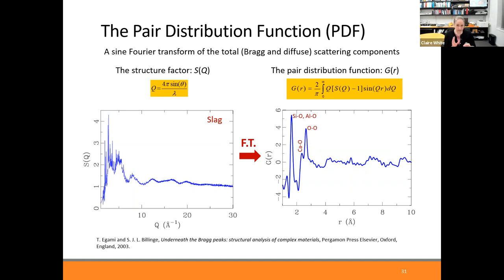And so that's what's shown on this slide, to actually get the pair distribution function from diffraction data. This is neutron data, and on the x-axis is momentum transfer, Q, which is related to 2 theta, the scattering angle, and the y-axis is intensity. And so here we're going out to high Q. If you think about a lab X-ray diffractometer using a copper X-ray tube, the highest Q max you can get is out to 8. So at synchrotron and neutron facilities, you can get to much higher Q max values.